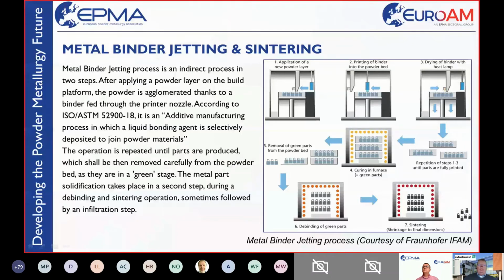Then you take these green parts into a debinding plus sintering step, and depending on the technology and material used, this debinding plus sintering can take place in one step, in one oven. This is really meant that the parts become smaller, as with a classically sintered part, so you have the classical shrinkage.